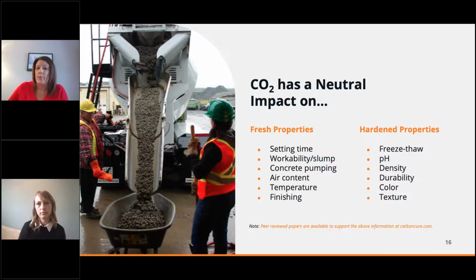So other than the impact on strength, there is no measurable or noticeable impact on any fresh or hardened properties. Fresh properties, we're not impacting set time, air content, workability, anything like that. Concrete temperature is not being impacted. We get asked that question quite a bit because it's CO2, a cold, dry ice material that we're adding, but it's a very small amount. As I mentioned, it's on average about a pound a yard, so it really does not have any impact on the temperature. And same with hardened properties, a neutral impact on all of those as well.